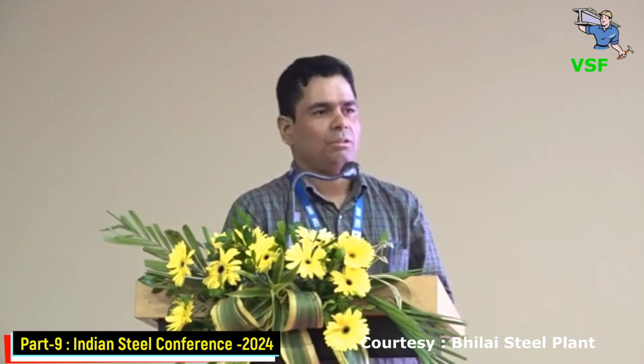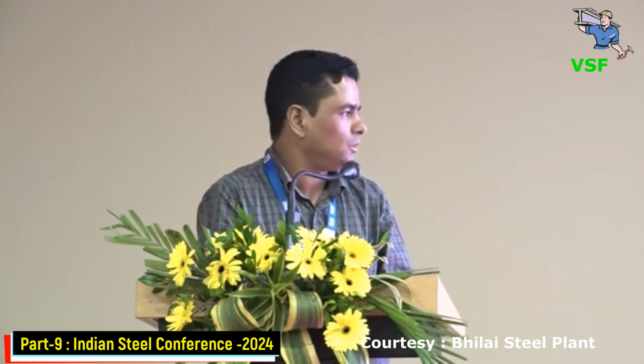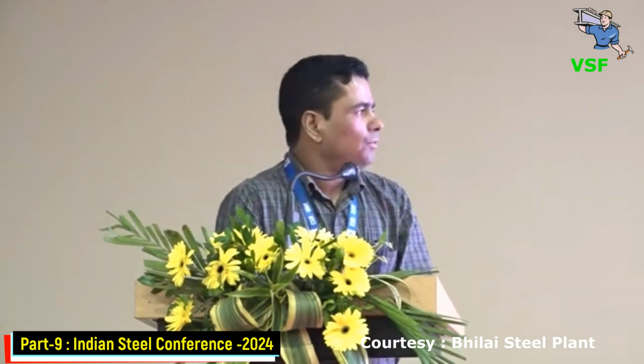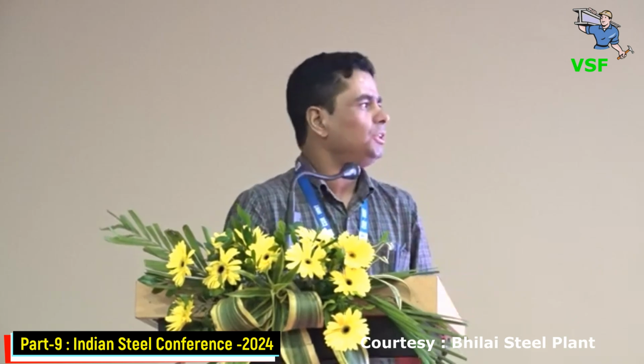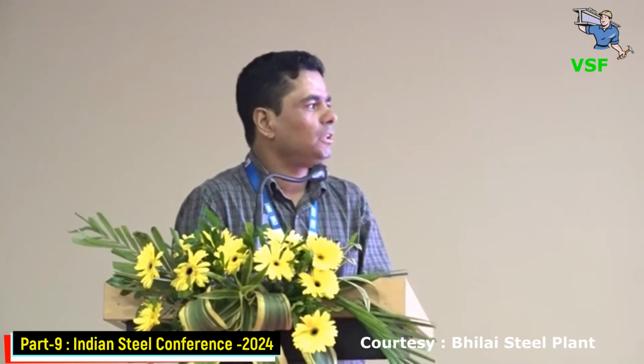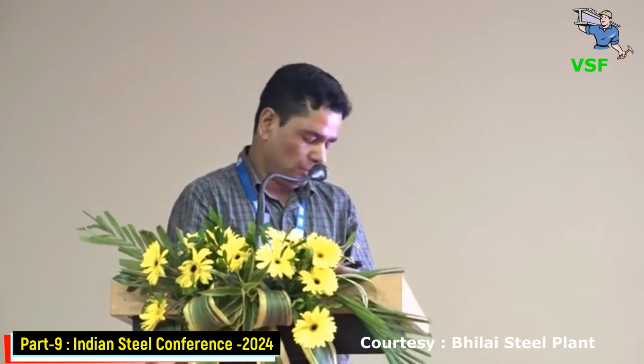Ultimately, we are getting a wide spectrum of product size distribution, and the energy cost is high in the grinding. And we know that in the mineral processing plant, grinding is the major energy consuming unit operation. Further, even if we try to do it somehow, we are still not getting the target of alumina and silica content in the final ore. So what we have been trying, actually this process has been tried and tested very well in other countries, primarily China, but we are refocusing this process with Indian ore characteristics, which are obviously different from other countries. So conventionally what we do,